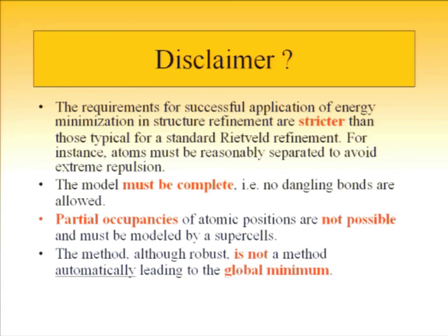Partial occupancies, which are typical for inorganic structures, are of course not allowed. Because from the point of view of quantum chemistry, the atom either is, say, silicon, or it is aluminum, there is no compromise, sorry. Either 14 electrons or 13 electrons. So if you wish to model partial occupancies, you should build a supercell, having one silicon here and an aluminum here, for instance, right? For 50-50.